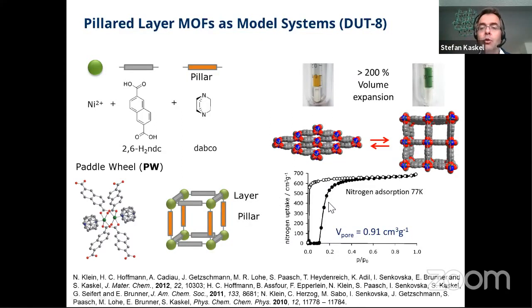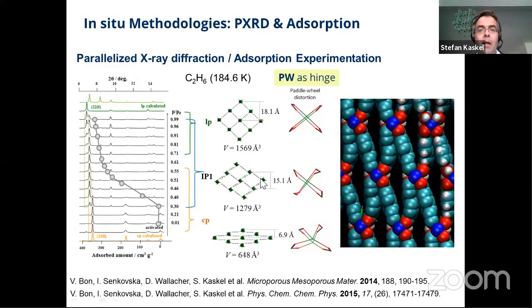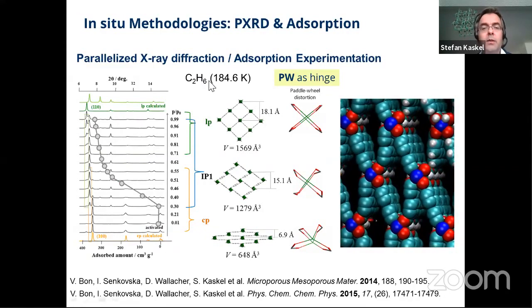And this material shows a huge volume change, a typical prototypical gating behavior, one-step gate opening. And at 0.1 in P over P0 in nitrogen adsorption, it basically opens the pore. And you can even see the volume expansion here very nicely in a syringe going from 0.1 milliliter to 0.2 milliliter. So you can even optically visualize this transition.